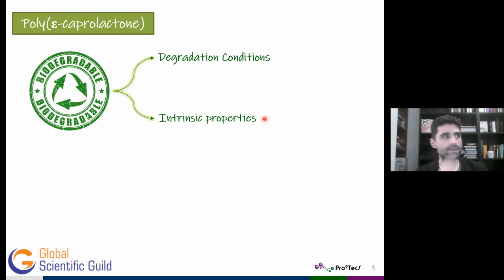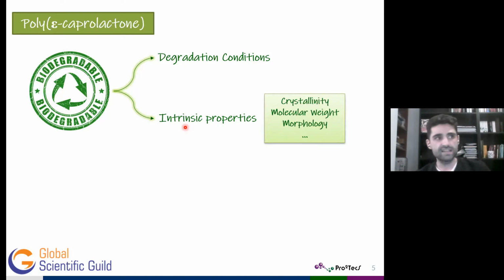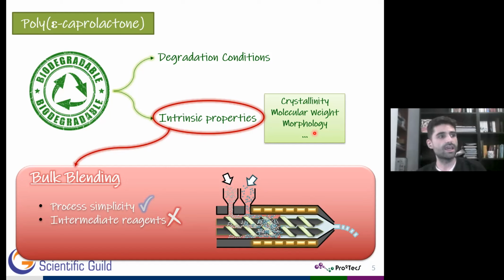On the other hand, the biodegradability of polycaprolactone strongly depends not only on the degradation conditions, but also on its intrinsic properties, including crystallinity, molecular weight, morphology, and so on. Bearing that in mind, the modification of the polymer network properties may allow us to somehow customize the ultimate performance of the resulting biodegradable polymer. In this respect, bulk blending of PCL with other materials has appeared as a feasible choice due to its process simplicity and the absence of additional reagents during this process.